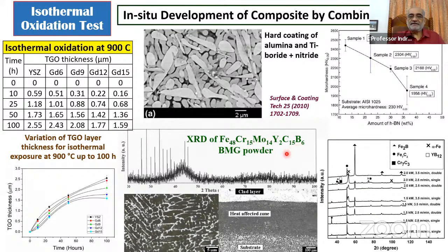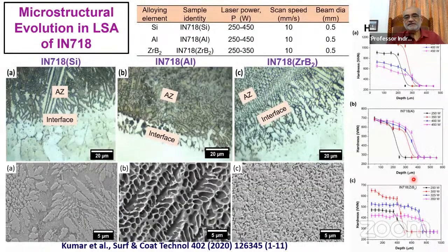small amount of melting time, if you have components like boron, carbon, or yttrium on one side and nickel or iron on the other side, even in that small melt pool residence time, the two elements, which are very different in density, melting point, and specific heat, have enormous attraction for each other, and they combine and form multiple carbides, borides, and so on. So it is no longer a single phase. The clad is very good, gives you wear resistance, but it's not a single phase product anymore. So this is just the metallurgical aspect of it.